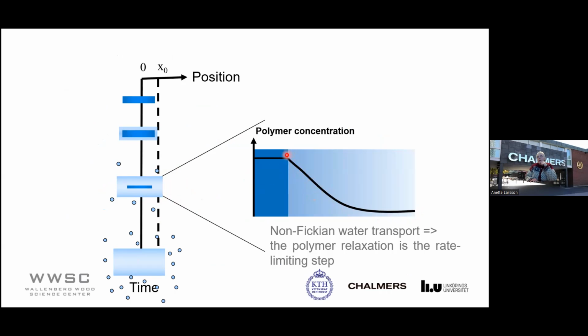We should pay a little bit of attention to this boundary here. The hydrophilic matrix tablets have a glassy polymer, most of them at least, start with a glassy polymer with a high Tg. When the water penetrates here, then the water plasticizes the polymer and the Tg decreases until it reaches 37 degrees, because that is the temperature we have.